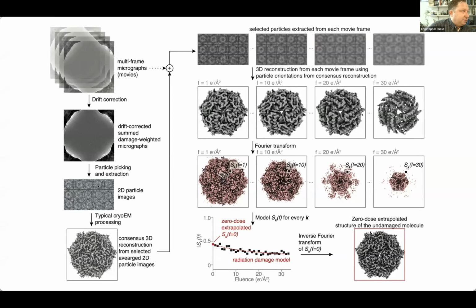So what does this actually look like in practice? We've now done this with quite a few structures since we've had these grids for a while now. So the data collection is just like normal. So you go collect your movies, lots of them, and you end up with 2D particle images, and then a typical cryo-EM processing yields a 3-dimensional map like this. And then this is where the new bit starts. So you take all of your 2-dimensional images that contributed to this and are a function of dose, and you create maps of each at each time point, or at each dose point, as it were.